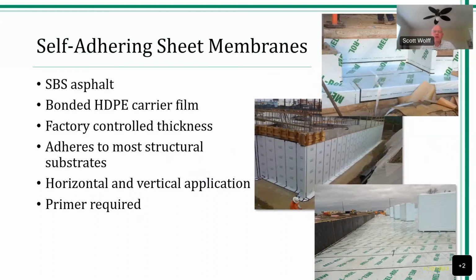This is a 60 mil self-adhering sheet that is a 4 mil high density polyethylene carrier film bonded to 56 mils of rubberized asphalt. Factory controlled thickness. We don't have to get our wet mil gauges out, so we know what we're getting every time. It adheres to most structural substrates, including even insulated concrete forms. We certainly have to be aware that we have to use a water-based primer, because self-adhering sheet membranes do require primer. But in horizontal application, this is my personal preference, I always prefer to have 2 plies, just simply due to that thing I mentioned earlier called gravity. Items get dropped, especially during the assembly. Having a second layer provides an added layer of robust, redundant belt and suspenders, if you will, protection.